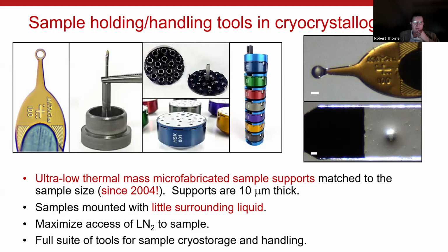They consist of a microfabricated thin film. It's about 10 microns thick. There's no plastic except for where the sample goes. Everything is nicely thermally isolated. It's exactly sized to match the sample. So you get very little surrounding liquid and excellent contact with the cooling fluid.